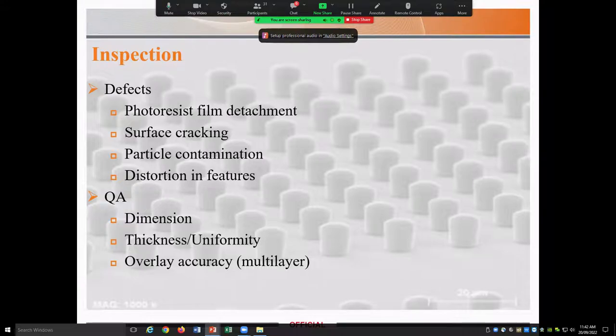And like the other types of fabrication processes, the last step is inspection. Optical microscopes or laser-based microscopes can be used in this step. The potential defects we are looking for are film delamination, surface cracking, particle contamination, or feature distortion. And also we need to check the dimensions, the thickness uniformity of the photoresist film, and the accuracy of the alignments.